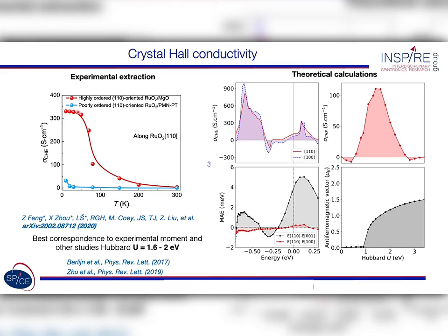The actual experiment agrees fairly well with the magnitude that we've predicted, and the orientation also seems to indicate that the order parameter is canted enough by this field to observe it. So in this case, this is indirect evidence that there is an agreement. We're doing further experiments to convince the experimentalists and the referees that we have a handle on the orientation of the ruthenium oxide order parameter, which is of course the challenge here from the point of view of observation. In this sense, this is not a spontaneous Hall effect, because the Néel order parameter is not spontaneously in the correct direction.